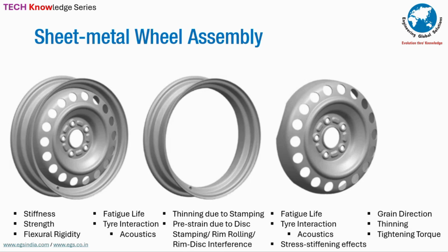Then the tire interaction in terms of the acoustics, in terms of moving away from the tire acoustic noise things. Can it be done? Absolutely. Then the stress stiffening effects, incorporating the grain direction, thinning, and the tightening torque. When you are taking the frequency analysis, if you are applying the tightening torque, you will get a frequency. If you are applying just an impulse hammer on a car wheel, normally placed without any pre-tension on the bolts, just simply placed, you look at the impulse hammer test, you will get a 10% variation. Can you believe it? 10% variation. Can finite element predict it to less than 0.1 hertz? Yes.